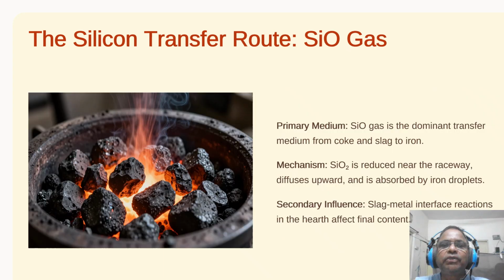Coming to our next slide, which elaborates on the silicon transfer route. SiO gas. Here is the aha moment. Silicon doesn't just fall into the iron, it hitches a ride on a gas. You see a close up of glowing porous coke, the black gold of the furnace. Inside those high heat zones, the silicon in the coke turns into SiO gas. Think of it like a silicon rich steam rising up through the furnace. As the iron droplets fall down, they act like little sponges, soaking up that gas as they pass through. If we don't control that gas generation at the bottom, the iron is preloaded with silicon before it even reaches the hearth. So if the gas is the vehicle, what are the speed limits we can enforce?